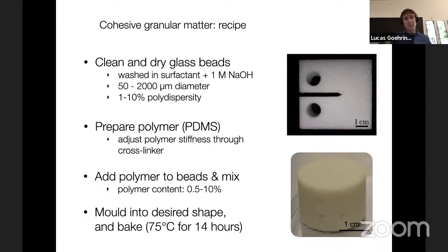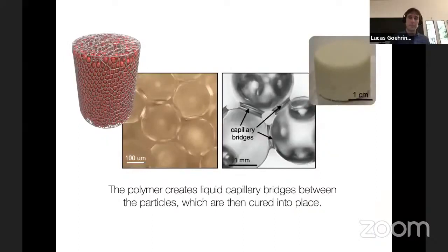We can also adjust the amount of polymer that we add to make the system have larger bridges, larger bonds between the particles, more cement, more matrix, whatever you want to call it, or less. This is something which is moldable. It has this sort of feel of cookie dough, and you can mold it into whatever shape you want. You can then bake it in the oven, again, like cookie dough, and you're left with something rigid. And then we take those kind of materials and we fail them in various ways. So these are an example. These are some pictures of what the material looks like under different conditions. On the left, we have an X-ray tomogram sample where we've identified the locations by some thresholding technique and identified the Voronoi cells.